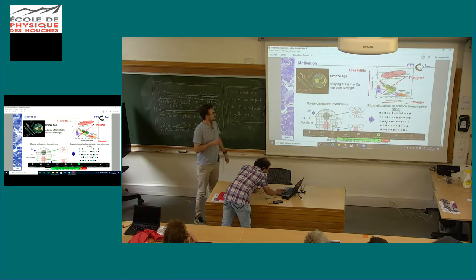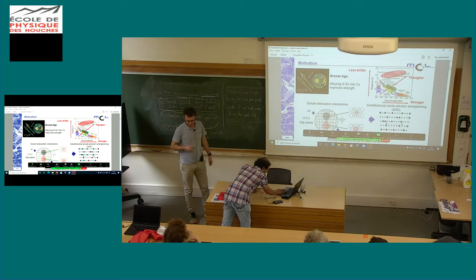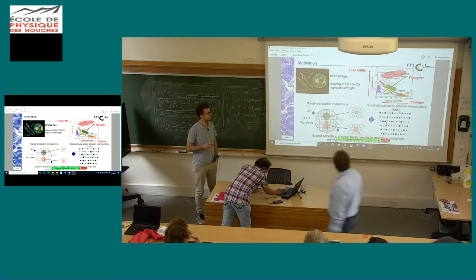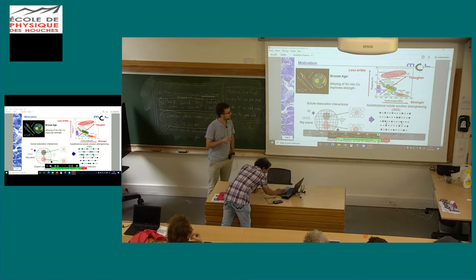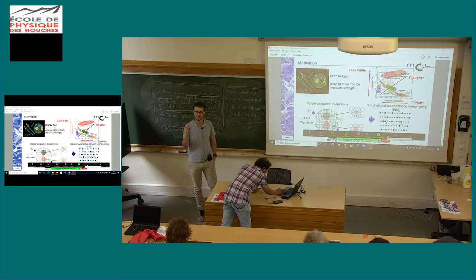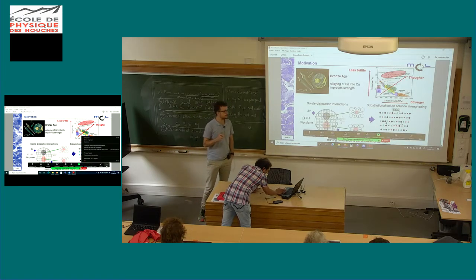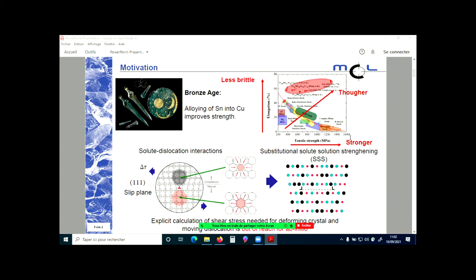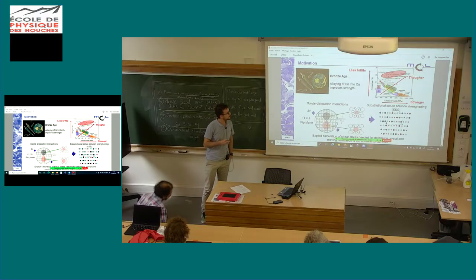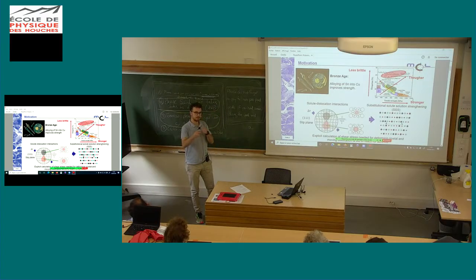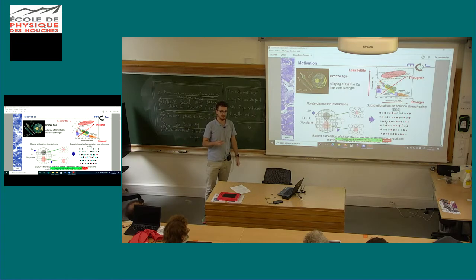So, in ancient times, people basically discovered that by alloying tin into copper, one can greatly improve its strength. But actually, what do we mean by strength? We mean essentially the stress at the onset of plasticity, but that's not the only important parameter here. It's also important to know how much more stress we can apply before the material fractures catastrophically. And a good measure for that is the toughness.